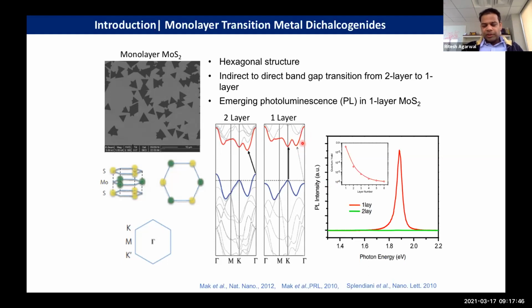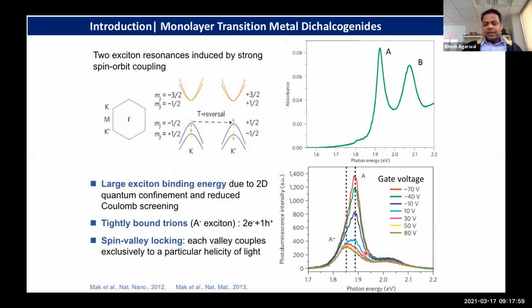And this, of course, has to do with orbital interactions in the z direction, which can shift the energy of the bands at the gamma point or the K point. So these materials are very interesting because when you thin them down to few layers, the excitons are not adequately screened. Because the electron-hole interaction is not screened, they can have very large binding energies of the order of few hundred meV. Claims are made of the order of 1 electron volt, but to be on the safe side, a few hundred meV.